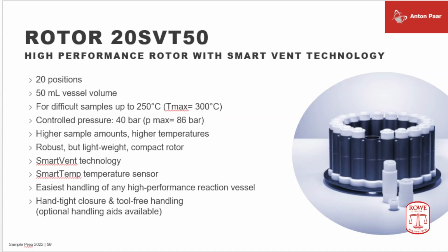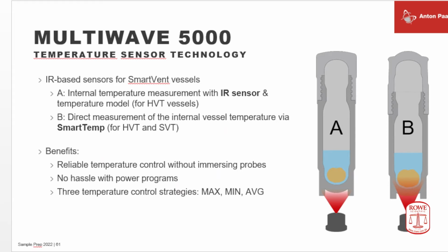Like said before, temperature is the most important primary parameter in sample preparation chemistry. And we have 2 types of infrared-based contactless sensors that are built into our Multiwave 5000. One is a classical IR sensor that measures the outer temperature of a reaction vessel and via a mathematical model calculates the temperature inside. This works very well when you have pressure vessels with thin walls, because then the temperature gradient from internal to outer side is not that big and the temperature transfer is quite quick. When we work with thick-walled pressure vessels, which can withstand higher pressures, we apply a new type of infrared-based sensor, which we call smart temp sensor.